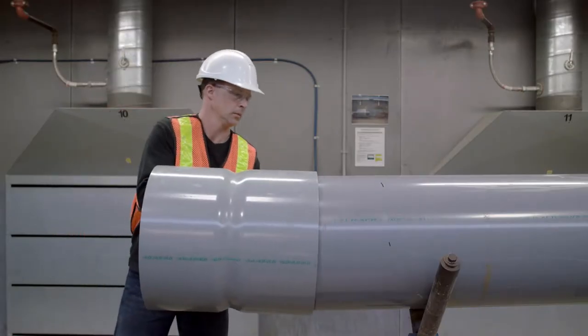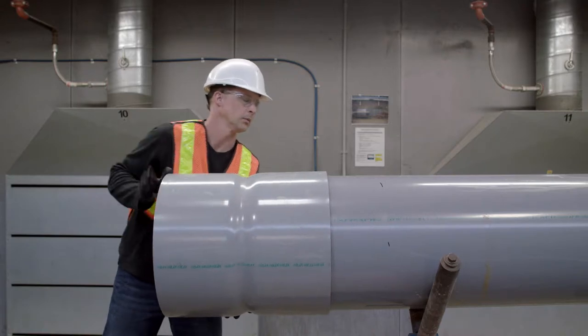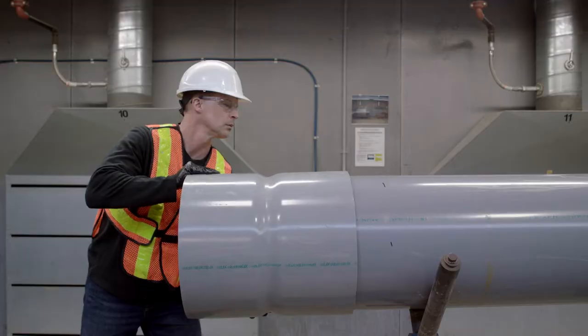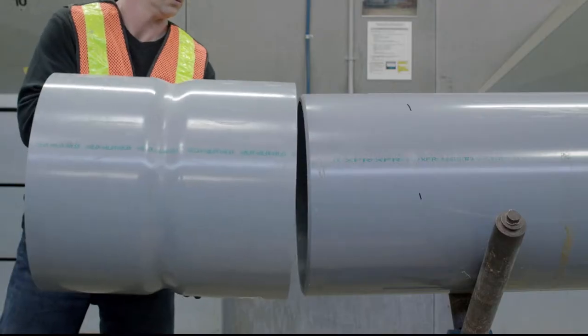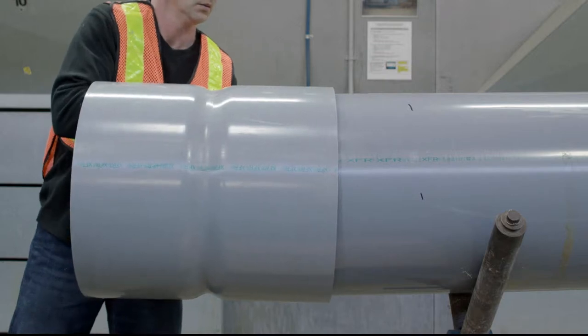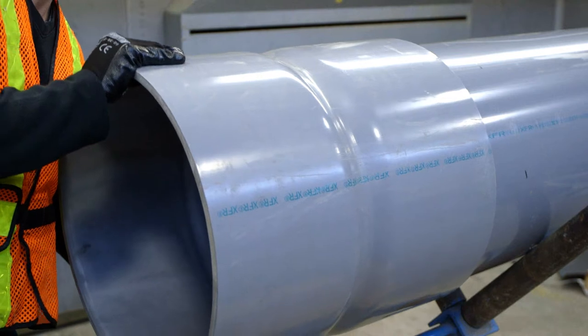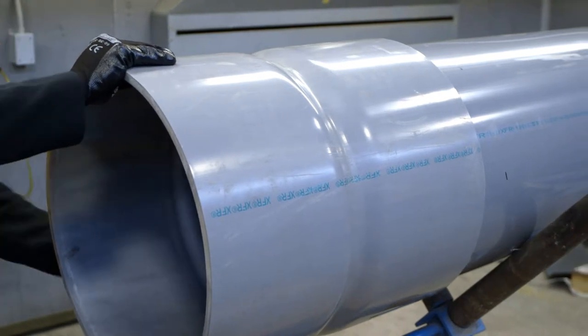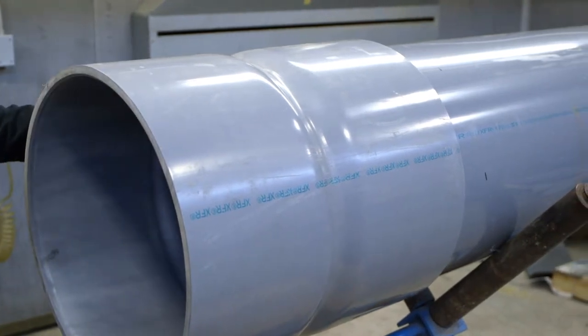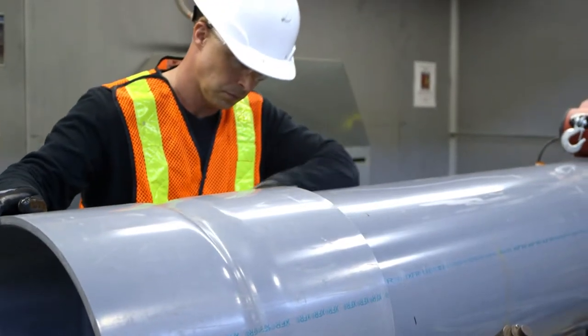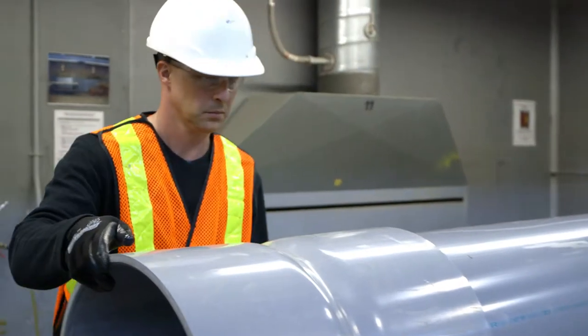Four: dry fitting. Before applying primer or solvent cement, test all pipe, fitting, and accessory connections to ensure a proper interference fit exists. Dry fit contact between properly beveled pipe and fitting sockets is essential in making a good solvent welded connection. The beveled pipe should easily enter the fitting socket and make contact with the socket wall before bottoming out. A proper interference fit is present when the beveled pipe can only be inserted one-third to two-thirds of the way into the fitting socket.